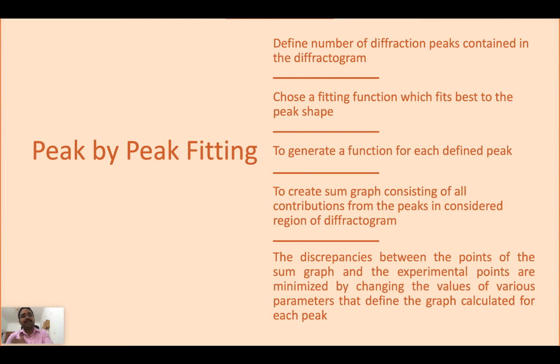Now when you have a diffractogram, we have to fit the peaks. Fit means I take a profile function, theoretically generate a peak for that experimental peak, and derive a 2 theta value. Once I have the 2 theta value, as I told you, 2d sin theta equals n lambda, with n equal to 1. Lambda we know, theta we know, so we can find the d spacing. This is the way we proceed for everything. For cubic you can calculate by hand, but when you go to tetragonal and other lower symmetries, you need a computer or computational system.